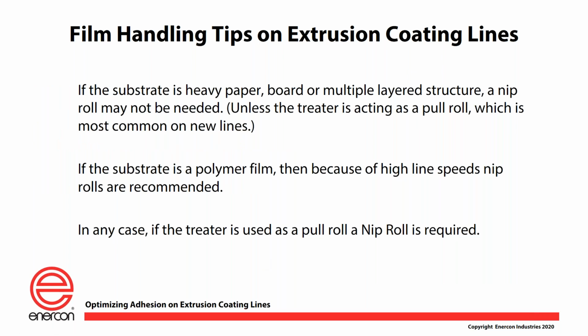Do I need a nip roll to help control that web against the treater roll? Well, if your substrate is heavy and you have a high web tension, such like paperboard, just heavier films, for example, where you're actually able to have some web tension on that material without any negative impact, then of course a nip roll probably isn't really necessary. Now that may change. That could change a little bit if you or your OEM partner decided to use the treater as an in-feed pull roll on that line. If that's the case, then regardless of what I just said, then the treater's got to have a nip roll, right? That just makes common sense.